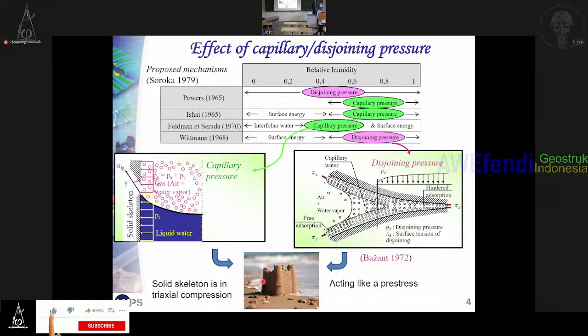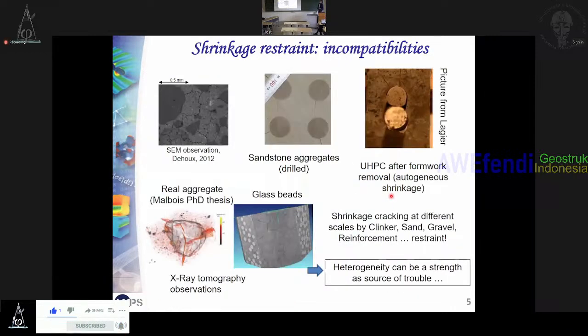In fact, if you are looking at the mechanisms of drying shrinkage, so capillary pressure, disjoining pressure, etc. Since the material is shrinking, in order to shrink, you should have compressive stress. So you have internal compressive stress that gives rise to drying shrinkage. So it acts like a prestress, so it will be positive. So that's why in the literature, you may find an increase or a decrease of mechanical properties. It will depend on the intensity of the compressive stresses related to these mechanisms, and also the gradient of shrinkage between the surface and the core.